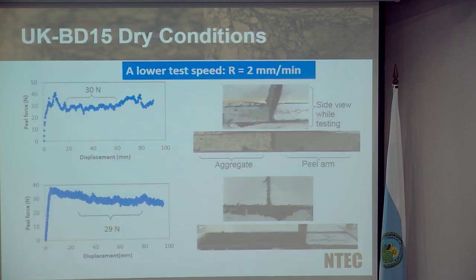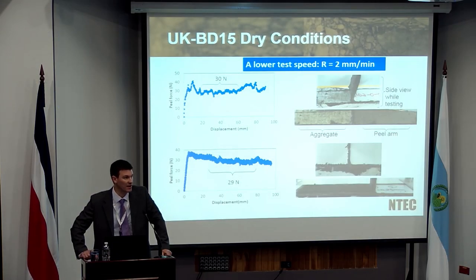I also mentioned that we would obviously want to test a whole range of different binders, and I showed you two examples: a very soft binder, which gave us relatively repeatable results, and a very hard binder, which tended to show a few errors in terms of crack jumping because the material was actually too stiff. This is exactly the same binder now, the 15-pen binder, and we've just reduced our displacement rate from 10 millimeters per minute down to 2 millimeters per minute.